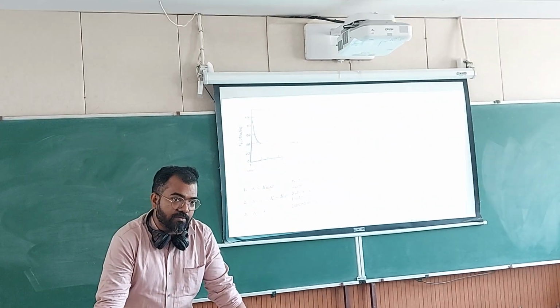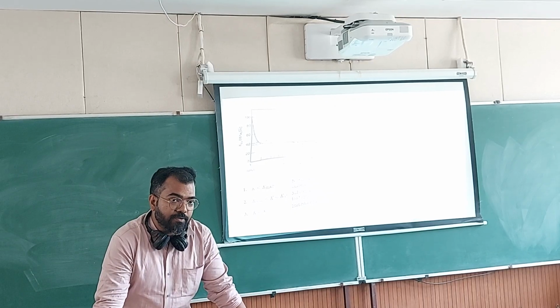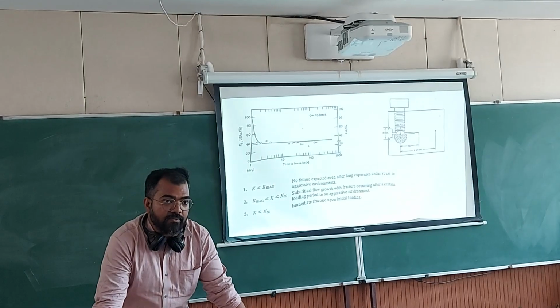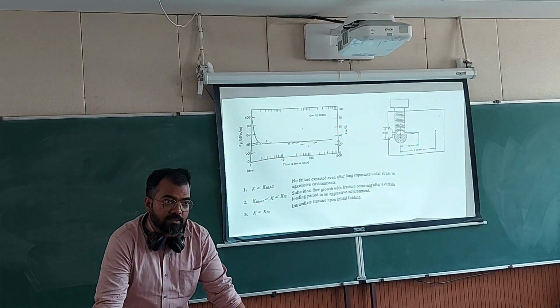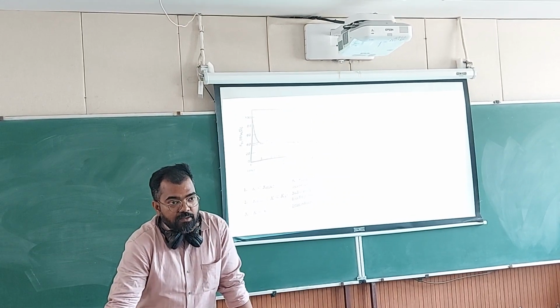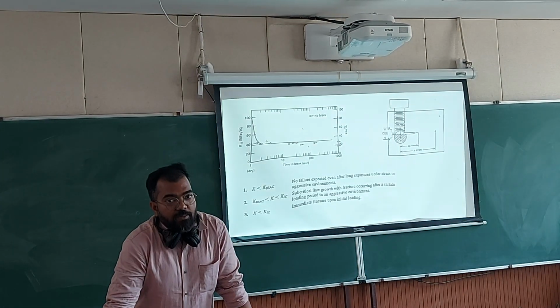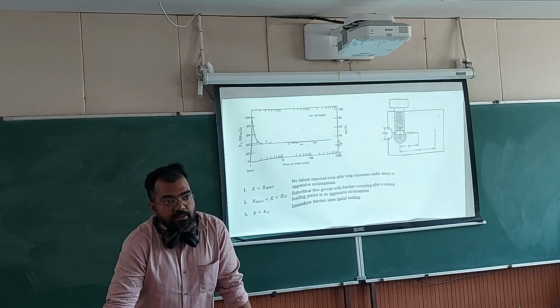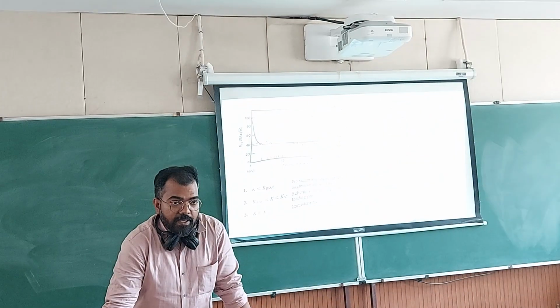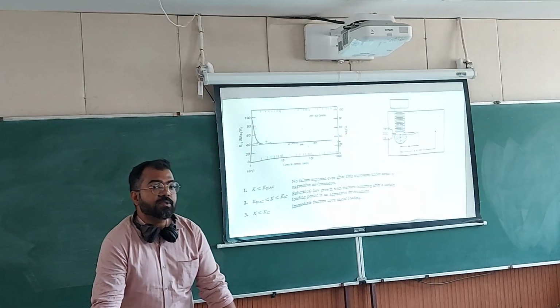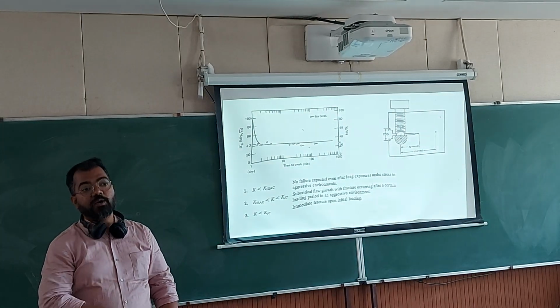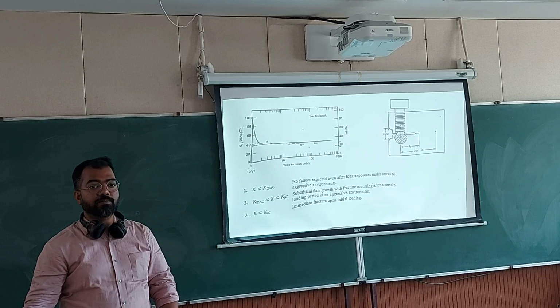So for every chemical reaction there is a threshold value of K. If your K is smaller than that threshold value, you will not have any influence on the critical stress intensity factor. Okay, and if you are beyond that, then the material is going to break. So this K1SCC is smaller than the K1C which you obtained without the influence of environment.